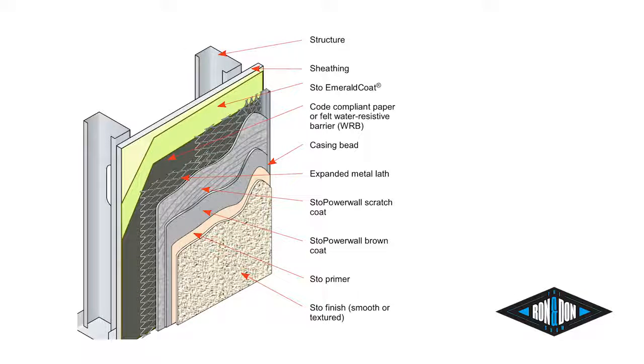Sure. So we're going to start with a hard coat stucco, and as we look at the hard coat stucco, all the systems are going to start with a sheathing of some type. Typically for hard coat stucco, it's going to be a wood. We're going to add a weather barrier. Here it's going to be 2 layers of 15-pound felt paper. We're going to add in our metal lath, which is going to be mechanically attached. We're going to put a cementitious scratch coat on. In a lot of cases, manufacturers today have one coat, so it'll be a scratch and brown coat combo. The thing to note is they should be no thinner than 5/8 of an inch thick.